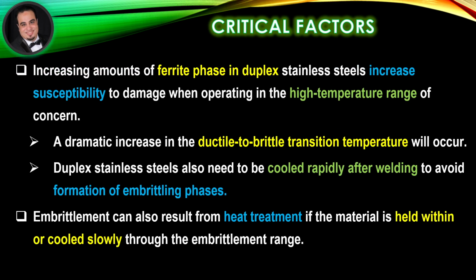Increasing amounts of ferrite phase in duplex stainless steels increase susceptibility to damage. When operating in the high temperature range of concern, a dramatic increase in the ductile to brittle transition temperature will occur. Duplex stainless steels also need to be cooled rapidly after welding to avoid formation of embrittling phases. Embrittlement can also result from heat treatment if the material is held within or cooled slowly through the embrittlement range.